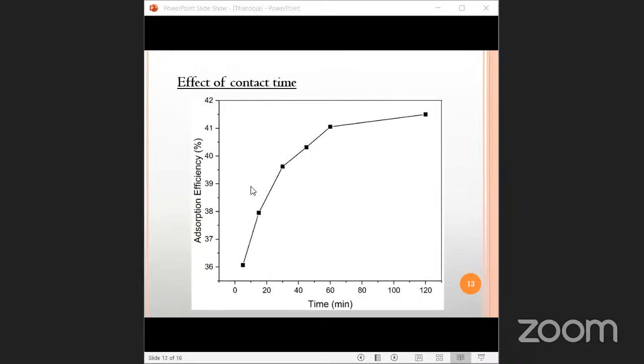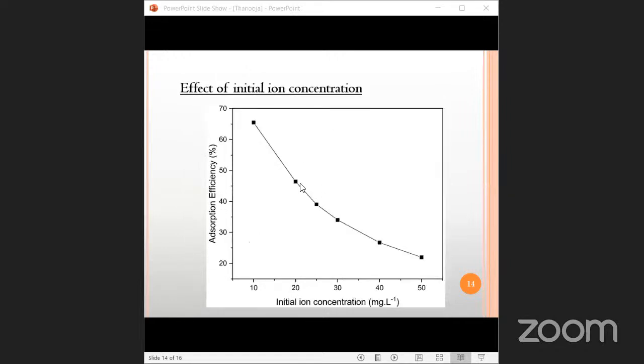Now, the effect of contact time. The adsorption efficiency was studied as a function of time from 5 minutes to 120 minutes. The rate of adsorption increased rapidly in the first few minutes because of the availability of a large number of active sites. The rate of adsorption attained equilibrium within 60 minutes and only a slight increase in the adsorption was observed after equilibrium. This can be due to the repulsive forces between the heavy metal ions on the adsorbent surface and the remaining ions in the solution.